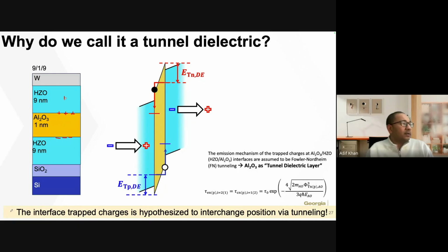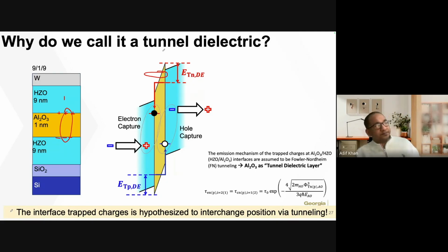And more importantly, our modeling was able to show that this dielectric layer, this 1 nanometer aluminum oxide dielectric layer, works somewhat like a tunnel dielectric. But nonetheless, it really showed or suggested that in this device, we have an interaction of polarization as well as tunneling mechanism. Both of these mechanisms interact with each other to give rise to this enhanced memory window functionality.